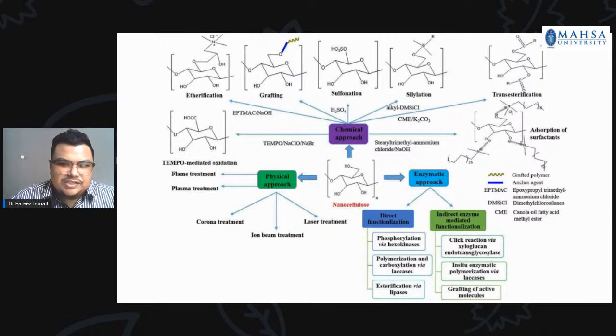Because of the hydrophilic nature of the nanocellulose, there are many hydroxyl groups on the surface, and the surface chemistry can be tuned chemically, through a physical interaction, or through a biological approach. That will result in surface functionalization, which can be done during the preparation step or after the production of the nanocellulose. And it can be done through incorporation of any chemical functionality.